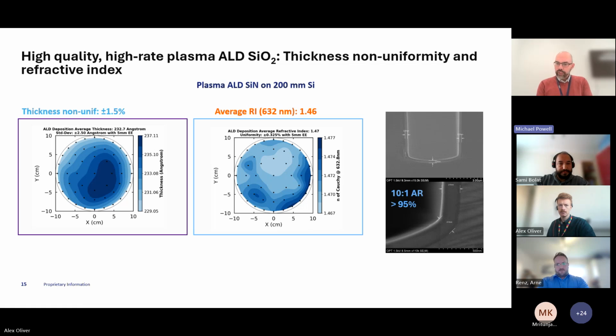And to briefly touch on what we can do with atomic layer deposition itself. Within the project, we had quite a broad remit, but what now seems to be shown to be the best material for silicon carbide at the interface is silicon oxide. So we've developed a silicon oxide ALD process that is high rate but high quality. We can do 100 to 150 nanometers an hour and deposit, as you can see here, with high conformality. We can get above 95% conformality on a 10-to-1 aspect ratio. When you look at the silicon carbide devices and where we're going with the MOSFETs, this gives you quite a good level of control for this film, so that you can have a gate oxide that really goes across the entire structure and deposits with high quality.